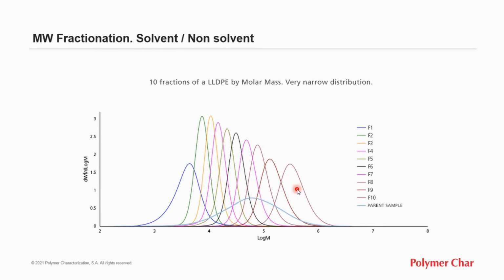Also, molar mass fractionation on a column with thinner support with solvent and non-solvent mixtures is possible. Again, here we see the molar mass distribution of the parent sample, which is broad, and then the molar mass distributions of the narrow fractions overlaid.